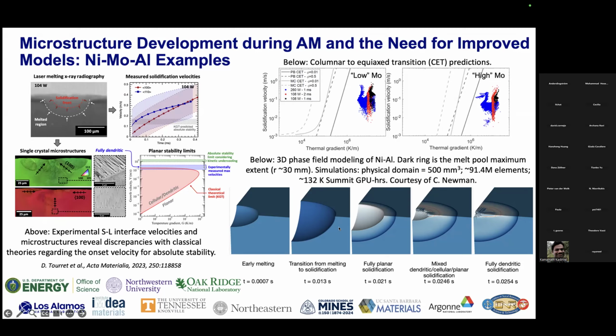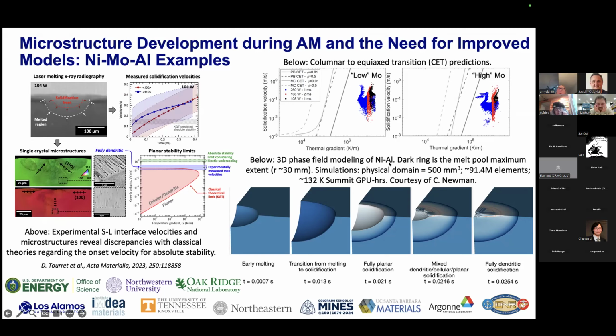And I want to mention this is a simulation done with exascale computing by one of my colleagues at Los Alamos National Laboratory of an approximation of this alloy of a nickel aluminum binary composition. So a full 3D melt pool simulation with phase field. So again, better trying to predict for multi-component alloys and also in 3D as well. And then above is just a nice example from Peter Voorhees' group at Northwestern, where they were doing some of this columnar to equiax transition modeling for us for multi-component alloys and making comparisons with our data.